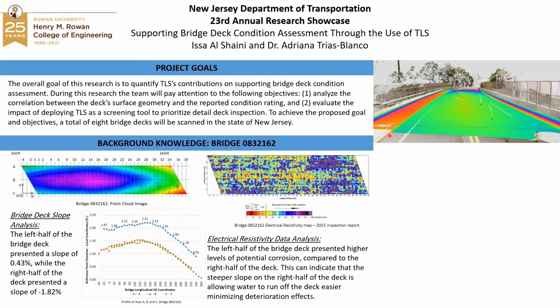The gradient in the middle of the bridge, the green region, shows a flat slope where the gradient is not changing. In the middle, it turns into yellow and darker, which can indicate a depression on the surface of the deck, which may lead to water retention and eventually lead to potential failure and corrosion. We were able to get the result by registering our scans and colorizing the scans to vary between different elevations. The right side here shows the sidewalk, and it shows that it elevates higher than the deck surface.